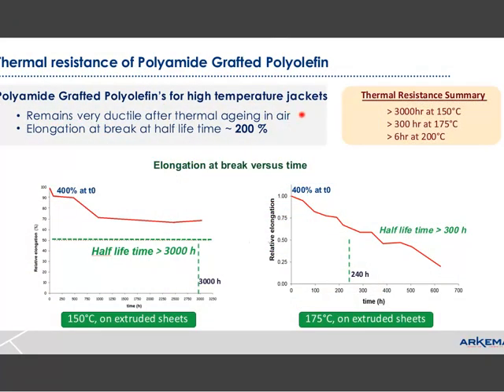One of the other benefits of these grafted polyolefins is their thermal resistance. A 3,000 hour test at 150 degrees C saw a relatively minor drop in elongational properties. Starting over here on the left at 150 degrees C, we're measuring elongation. You do have a drop in elongation, and then it levels out with a 30% drop in ultimate elongation that pretty much continues after 3,000 hours.